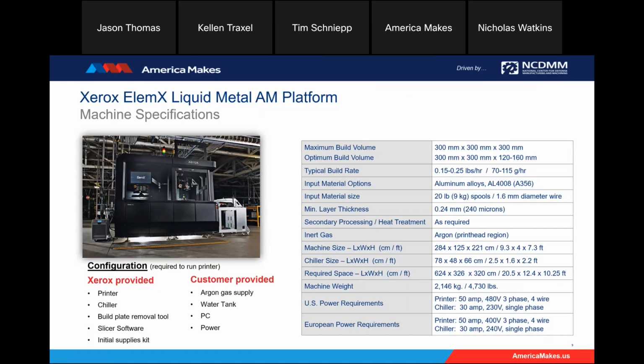And it does depend a little bit on geometry. We have built parts taller than 160 millimeters successfully as well, but that can vary. But I did mention we're adding thermal controls to the chamber itself. It's going to be an actively heated chamber, and that's what will extend that build size up to the full build volume. So that's coming later this year, and as I mentioned, that's a retrofittable change. We try to take that approach from a development perspective, that any updates and enhancements we do over time, which is at a pretty rapid rate, we can then incorporate into existing printers that are already in the field. And then the rest of the specifications are shown there as well. And like I said, I'm happy to provide a copy of this for reference.